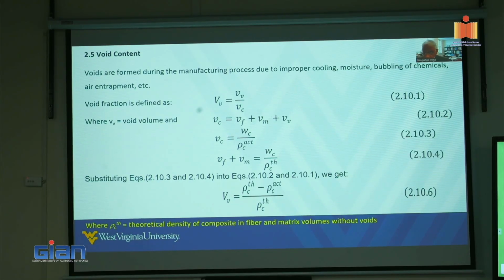And the volume fraction equations that I showed there are from 2.10.1 to 2.10.6. Finally, the final equation at the very bottom is the void volume fraction: rho c theoretical minus the rho actual, divided by rho c theoretical, gives you the void volume fraction. The measurements are not easy to establish, but under the scanning electron microscope, we were able to measure the void content with a reasonable degree of accuracy.